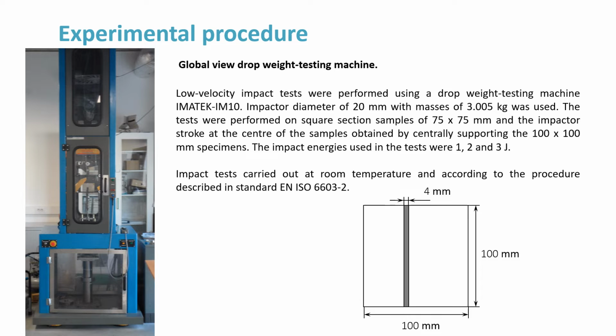Low-velocity impact tests were performed using a drop weight testing machine, IMATEK-IM10. An impactor with a diameter of 20 mm and a mass of 3 kg was used. The tests were performed on square section samples of 75 by 75 mm, with the impactor striking at the center of the samples, obtained by centrally supporting the 100 by 100 mm specimens. The impact energies used in the tests were 1, 2 and 3 joules.